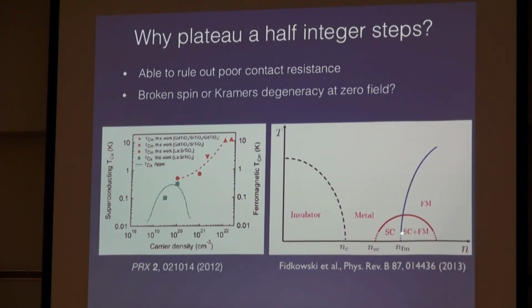So it's interesting because this superconductor plus ferromagnetic situation is exactly what we're looking for for Majorana physics. We need something that has superconducting correlations and that breaks the B equals 0 Kramers degeneracy. And the fact that these are all integrated into one system, and a system where you can tune throughout the device which ground state you have, might be a very interesting way to try to get at these Majorana fermions.